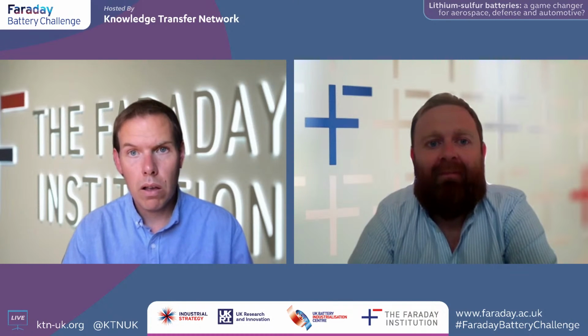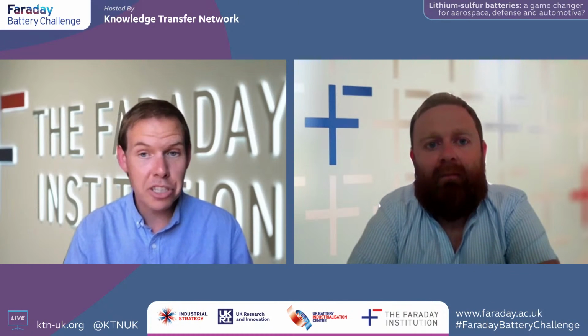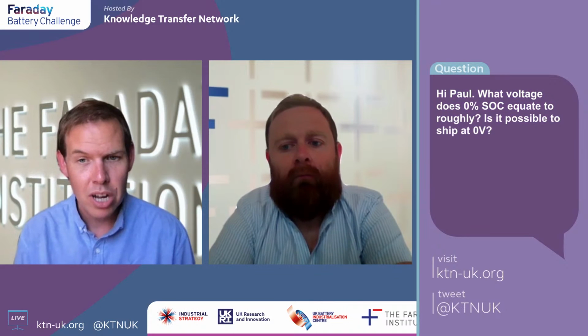A straightforward question, hopefully. What voltage does a 0% state of charge equate to, roughly? I.e., do they discharge all the way down to zero? You can discharge them all the way down to zero, yeah. If you look at a lithium-ion battery, you're probably looking at shipping at about 30% state of charge, principally because of some of the reactions between the active materials and the current collectors at very low voltages. That's not a problem that we have in lithium-sulfur batteries. So they can be shipped at 0% state of charge at 0 volts.